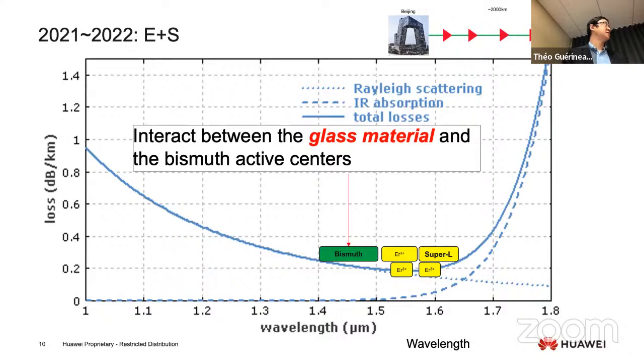And bismuth is an amazing ion. Although the physics behind it is not 100% revealed yet, people have currently successfully found ways to make fibers that can show promising amplification performances. Based on our recent research here in Quebec, we found that the bismuth-doped fiber amplifiers, if assisted by the erbium-doped amplifier, can provide more than 90 nanometers amplification bandwidth, covering the whole E and S band, and the output power can be well above watt level, and the noise figure, based on my calculation recently, can be very close to the quantum limit of 3 dB.